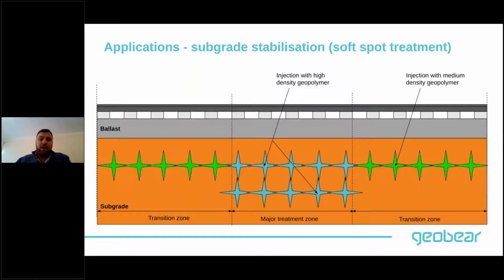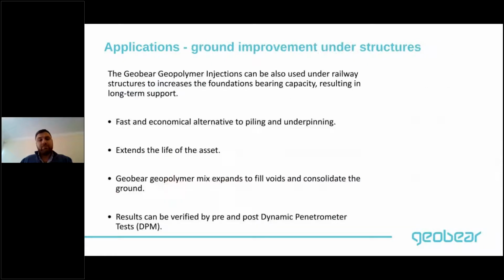Okay. We can use this technology to also treat discrete soft spots, for example. So if you've got a soft spot somewhere in the middle of the track, quite discrete, small, you can actually go in and start injecting it in this sort of approach where you inject a very strong geopolymer into the subgrade, into the soft area, and then start ramping out the treatment so you can create a nice ramp to the treatment. And this is how you can treat soft spots.